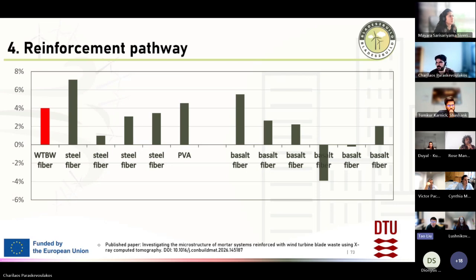This is a comparison. If we have these materials, how do they compare to other materials? We investigated, comparing with the literature, steel fiber, PVA fiber, and basalt fibers. Our wind turbine blade fibers here are at 0.5 volume percentage. They show comparable reinforcement cases. We know that steel fibers are very good, but in some cases we are a little bit higher than the steel fiber as well. But in general, they are comparable to all the other fiber reinforcement materials.